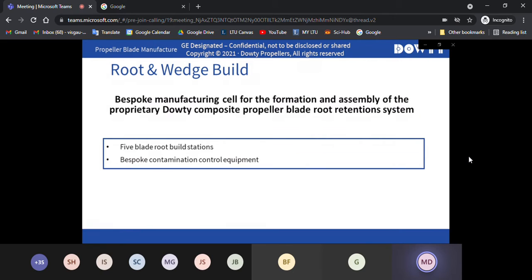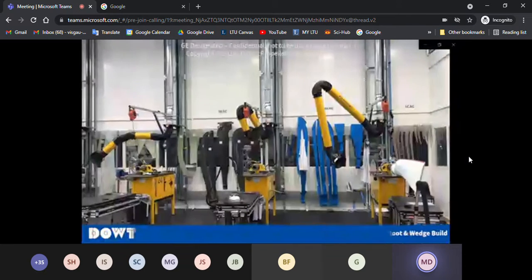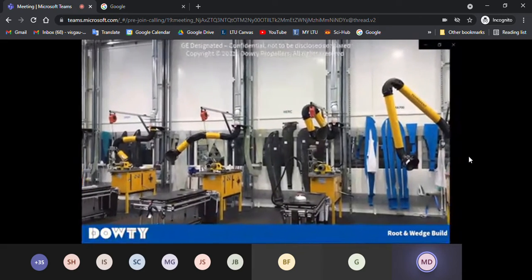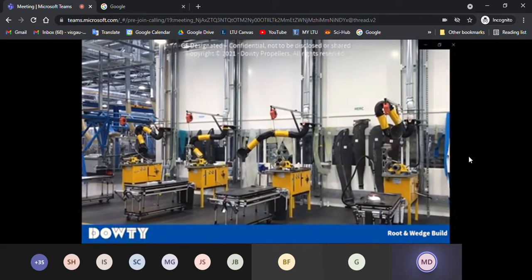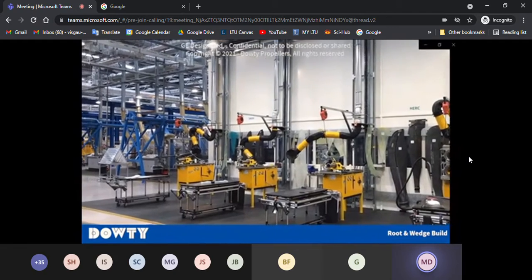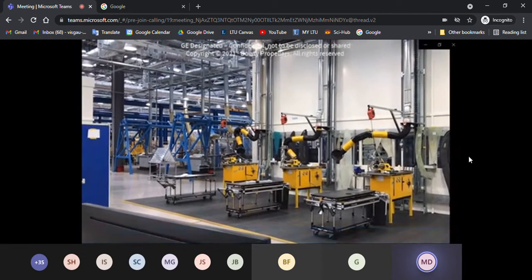Unfortunately, there's very little I can show you because it's very proprietary, the way that we attach the composite blade to the metallic root fitting. But we do have a series of individual stations you can see on screen to which the blade preforms are mounted, and we do the special preparation and attachment of the metallic root fittings prior to resin injection. At that point, the dry composite is completely finished and is ready for resin injection.